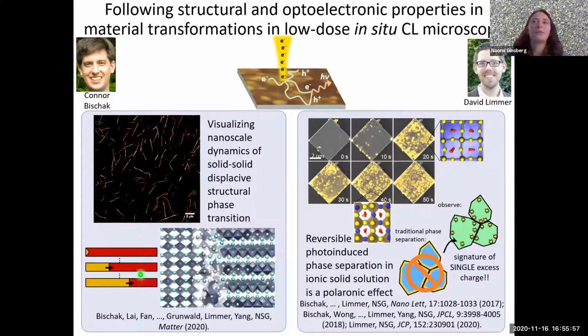And a really cool feature that we discovered thanks to simulations by Fan from Michael Grunwald's group is that despite the apparent disorder that you see here at this interface, ion correlations are strong enough that the emergent perovskite always orients in the same direction with respect to the original phase. Okay, and second, together with David, we uncovered a polaronic mechanism for a photoinduced phase transition in halide perovskites containing a mixture of two different halides, for example, here in blue and gold.